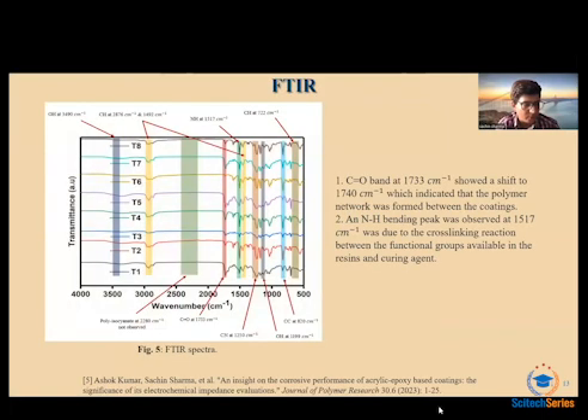And now we can talk about the results and discussion. So we can look at the FTIR results from T1 to T8, and we can see that there was a CO band at approximately 1733, which shifted to 1740, and this indicated that there was a cross-linking that had occurred between the coatings or within the polymer matrix.